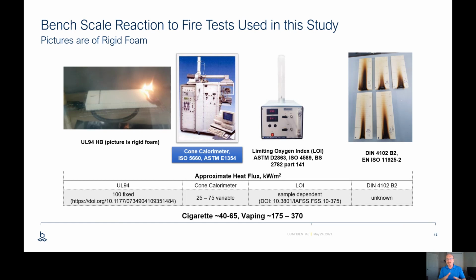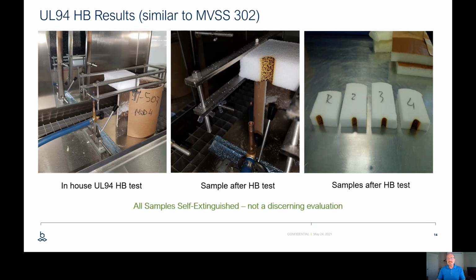You can see the cigarette at 40 to 65 kilowatts per square meter. So we thought, well, we can use the cone calorimetry and pick a number, and it seemed that 25 was a reasonable number based on what we were reading, and we'll go ahead and test everything at 25 kilowatts for those systems. Yeah, we did do some evaluations, UL94HB.